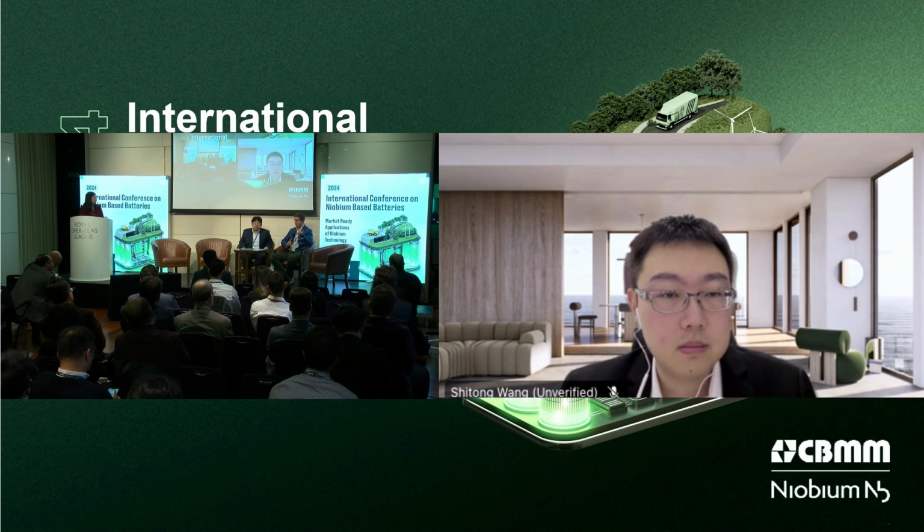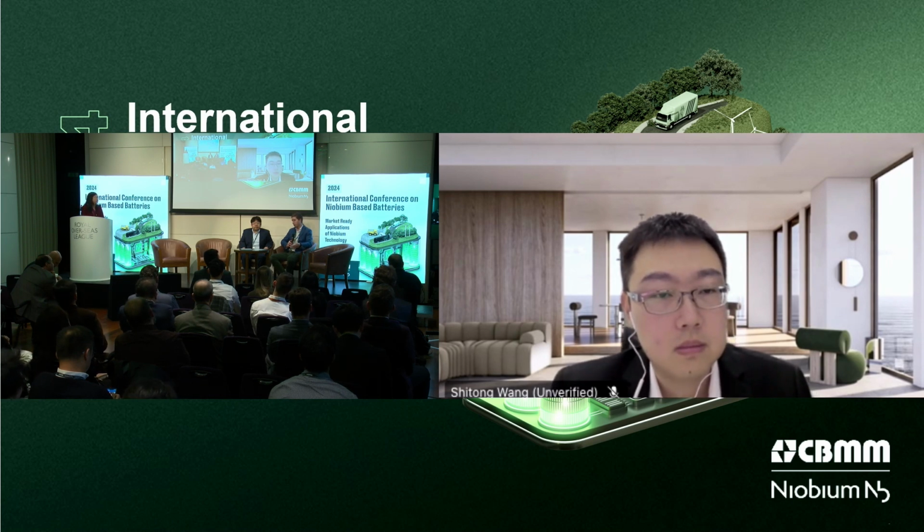In some sense, I would argue that's not a fair comparison, right? Because you need to either try to measure the same transport, or you need to try to recondense that material. So, again, we pressed cold pellets of it. It's not perfect, but you're doing the same thing with all the materials. Because otherwise, it's just saying, look, I had two particles and I separated them slightly, and now they don't have good conductivity between them. Yeah, it's not surprising.